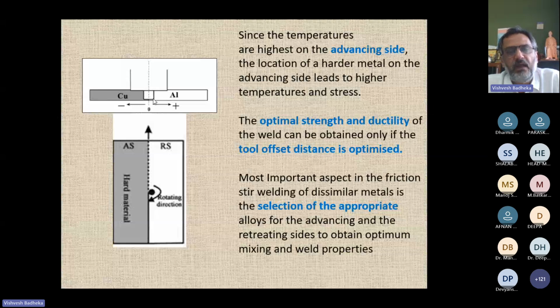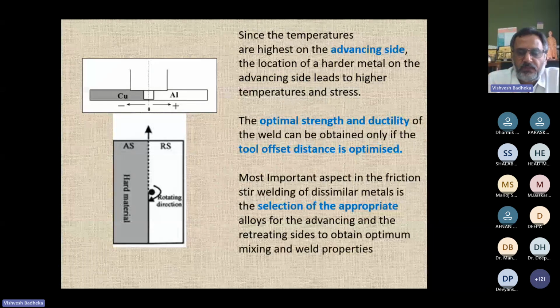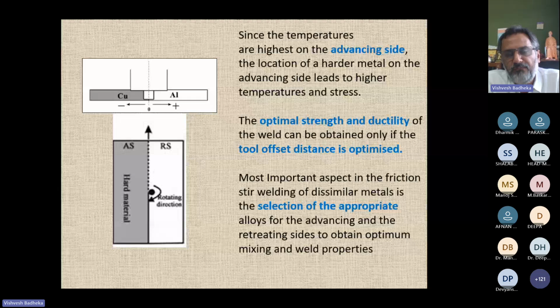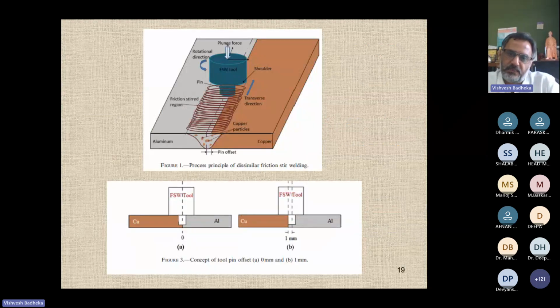So you can see here, it's very simple mathematics. I have a pin, and say for example, my pin diameter is 6 millimeter. So half of the pin diameter is what? 3 millimeter. So my maximum offset cannot be more than 3 millimeter. If I start with 3 millimeter, the contact with the hard material will be minimum. Then from 3 millimeter, I can move to 2.5, then 2, then 1.5, 1. So that's how my contact with the hard material will go on increasing. And that's how you can play with the different offsets and optimize the strength and ductility of the joint. So this is a very, very important parameter when you go for dissimilar metal joints in friction stir welding.